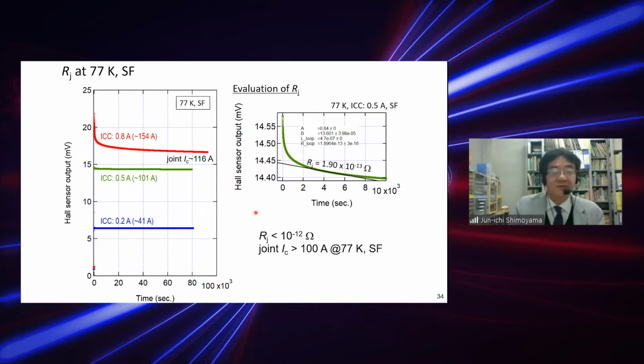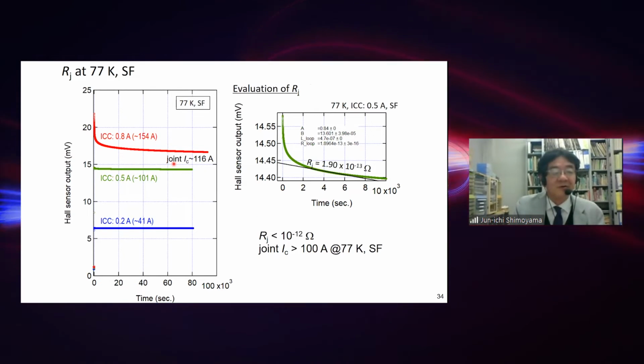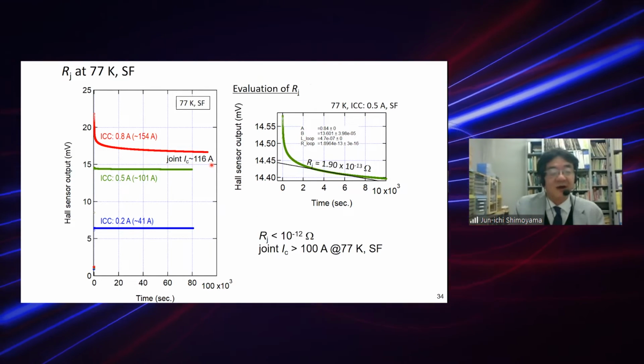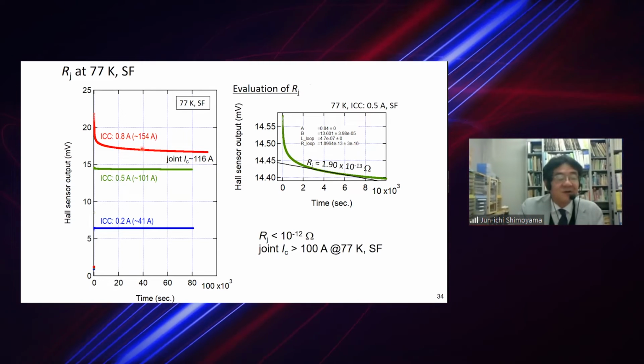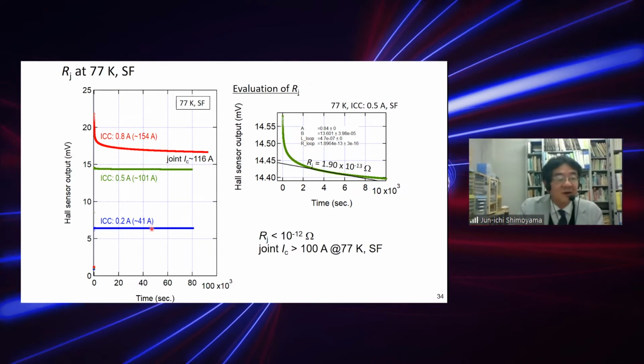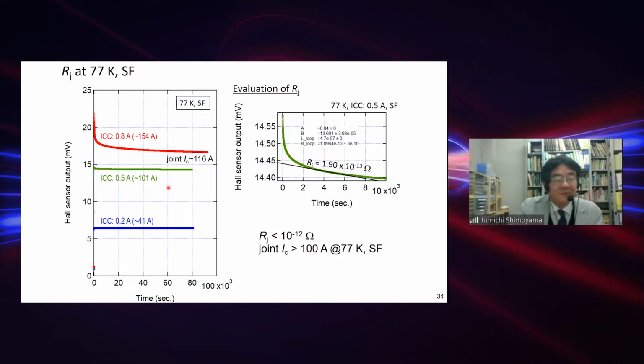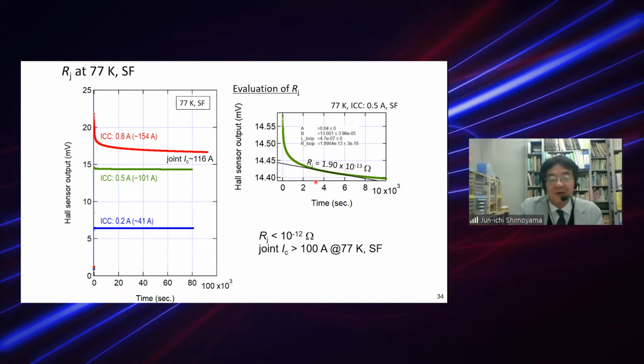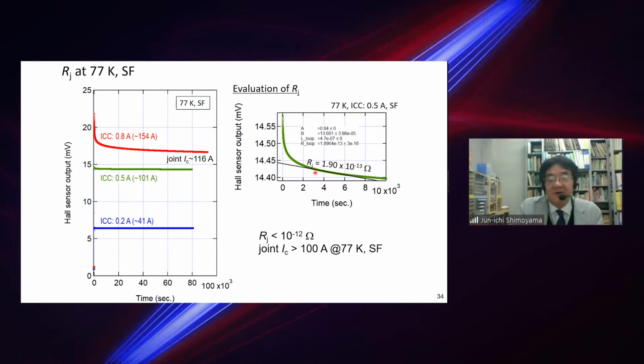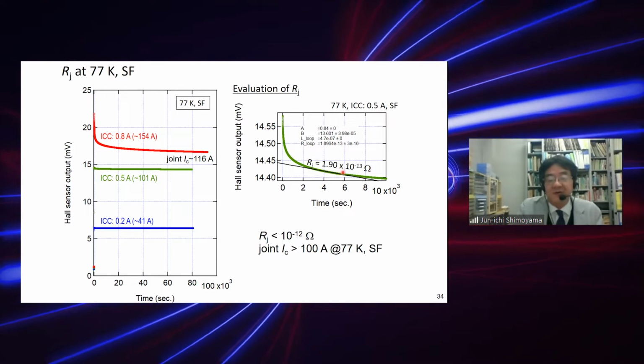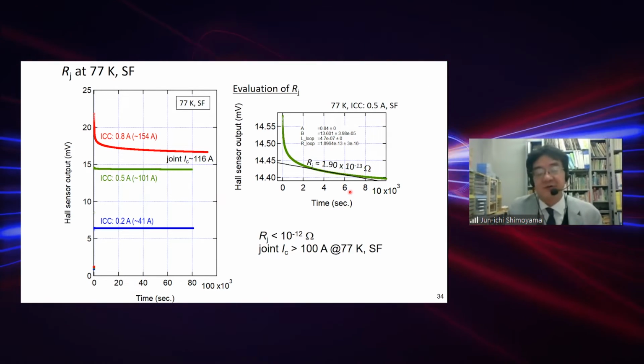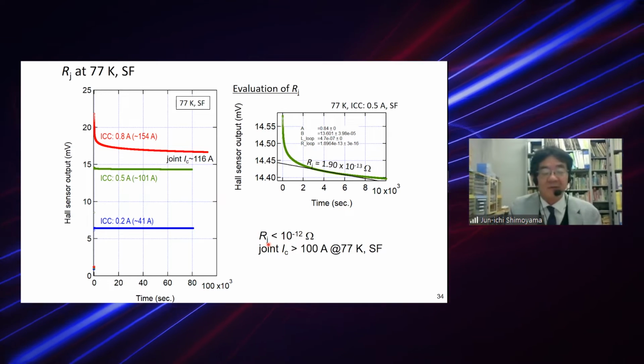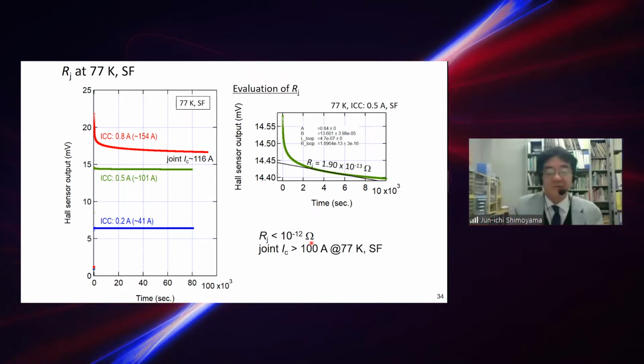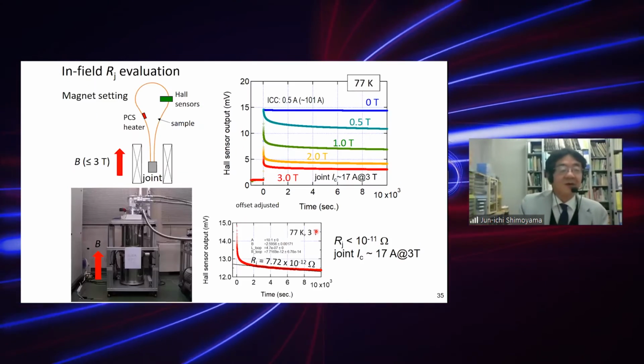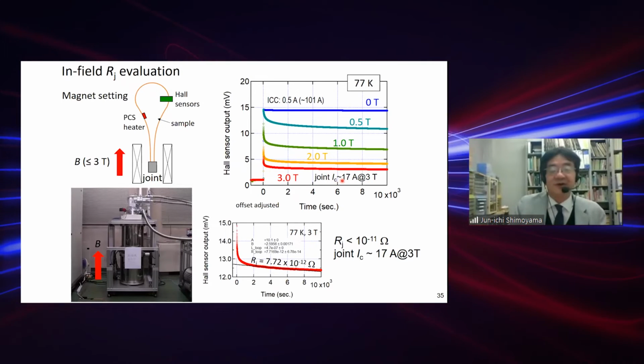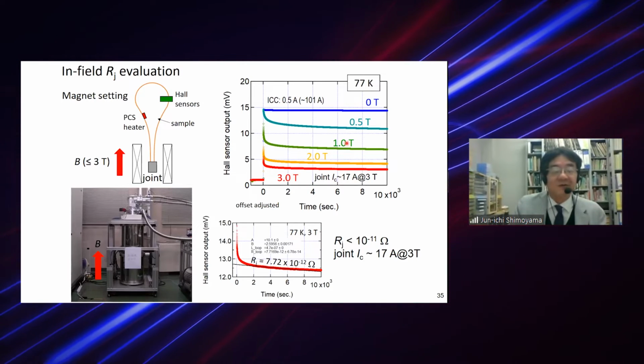So at 77 Kelvin, in this case, the joint IC is 116 amps. However, this joint can carry large current up to 100 amps without serious decay. In this case, joint resistance was 2 times 10 to minus 13 ohms. This also meets the required value of 10 to minus 12 ohms. So in-field performance at 77 Kelvin is not so nice.